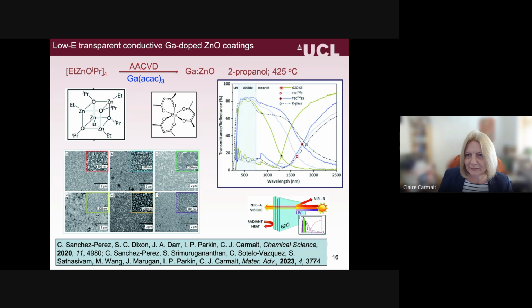And here I'm comparing our GZO, our gallium doped zinc oxide, in green, and I'm comparing this to some commercial low E coatings, which are known as things like TEC 8 and TEC 15. They're based on fluorine doped tin oxide. So you can see ours is performing comparably or even better than the commercial coatings.